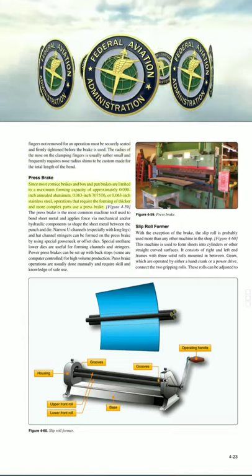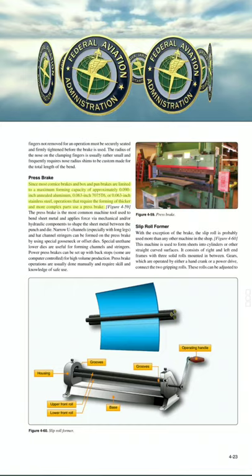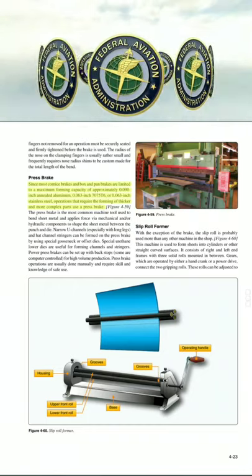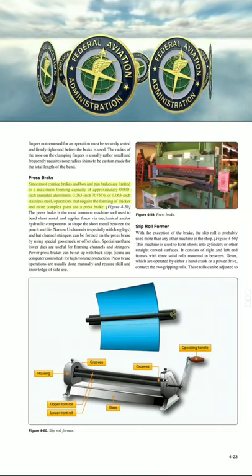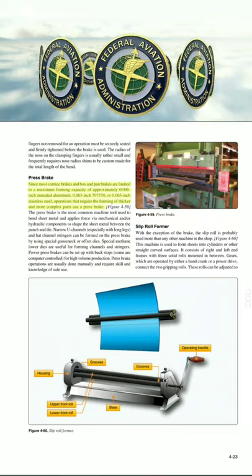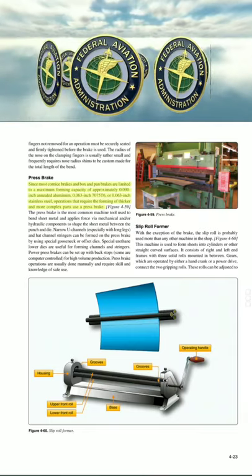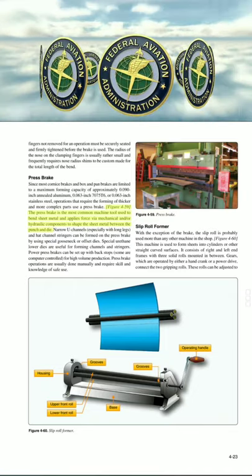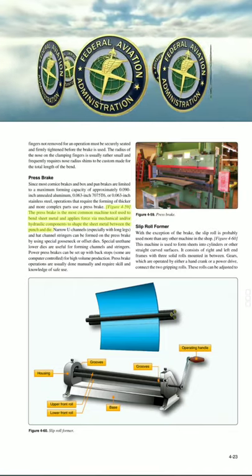Press brake. Since most cornice brakes and box and pan brakes are limited to a maximum forming capacity of approximately 0.090 inch annealed aluminum, 0.063 inch 7075-T6, or 0.063 inch stainless steel, operations that require the forming of thicker and more complex parts use a press brake. Figure 4-59. The press brake is the most common machine tool used to bend sheet metal and applies force via